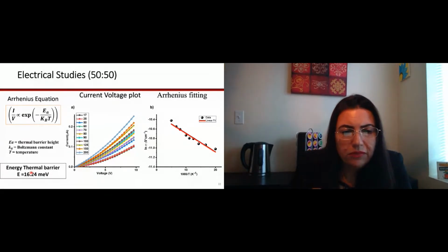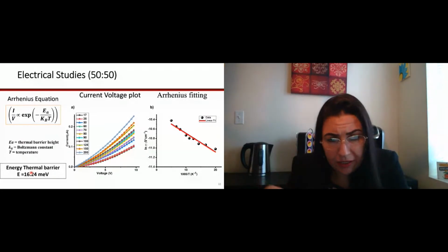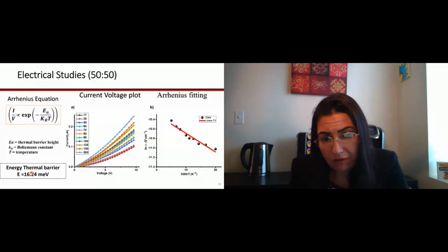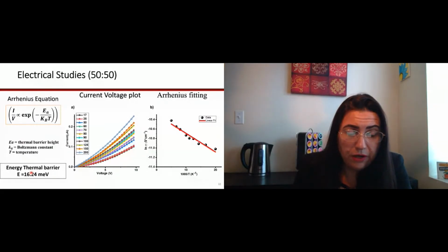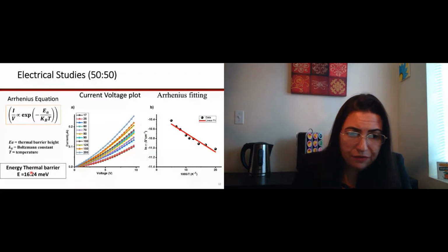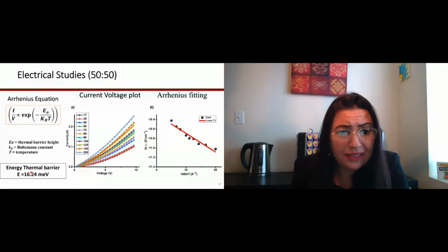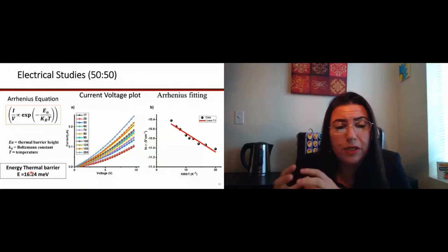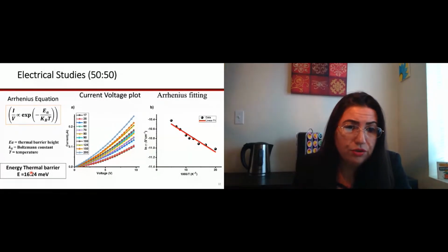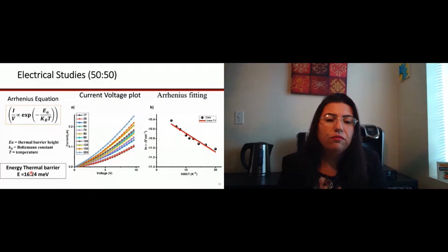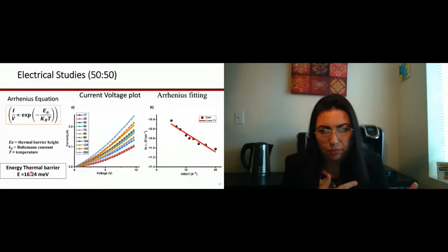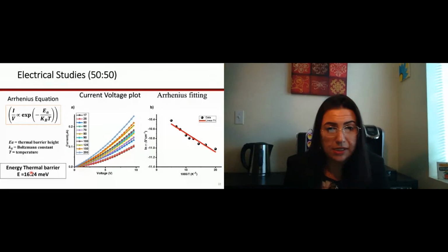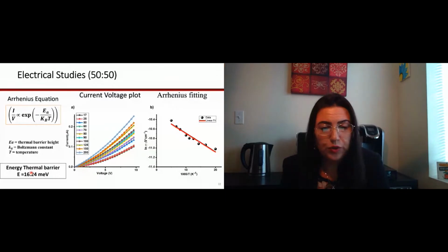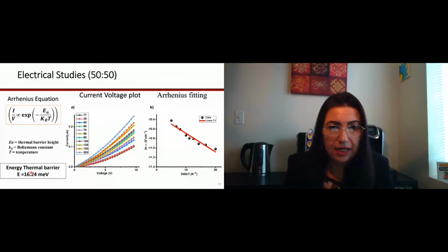This Ea over here is how much energy we need for the electrons to start flowing. So this value is a little bit higher than if we have just graphene. In this case, 16.24. For the graphene it is about 8. So that means that we need a little bit more energy for the electrons to start flowing. That relates to the conductivity properties that I mentioned before, the on and off switch that you would need for the electronic application.